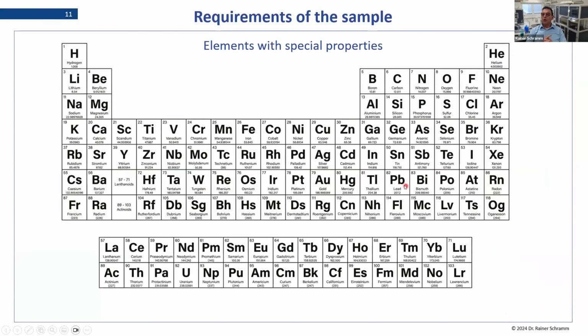Okay, but if we look on our periodic table, there are some elements which behave in a special way. The first group is here from chromium to copper, because they reduce the surface tension of our melt, which then tends to sticking. That means our bead will release not very easy from the mold. And this is because these elements are there in a high concentration.